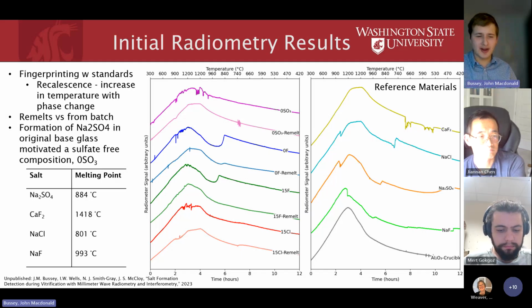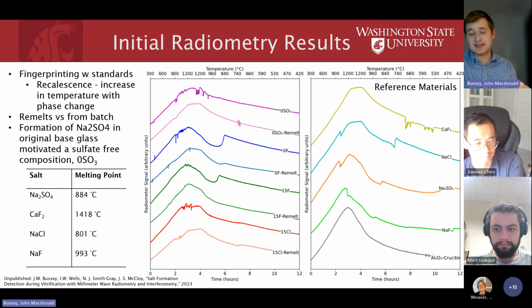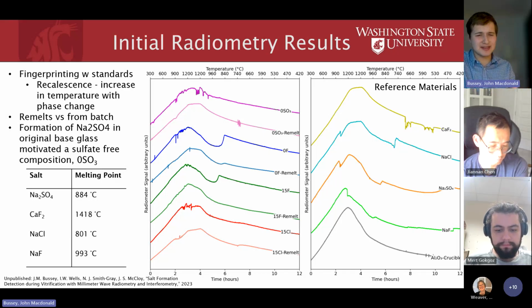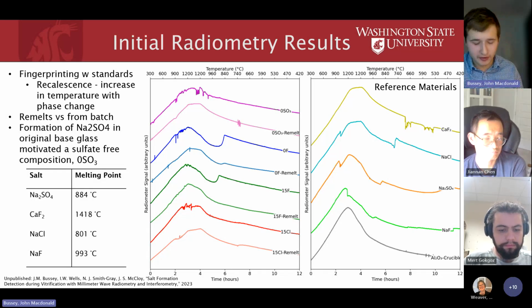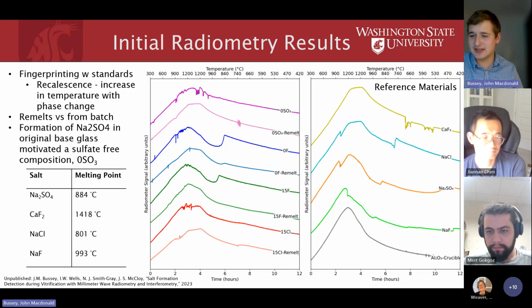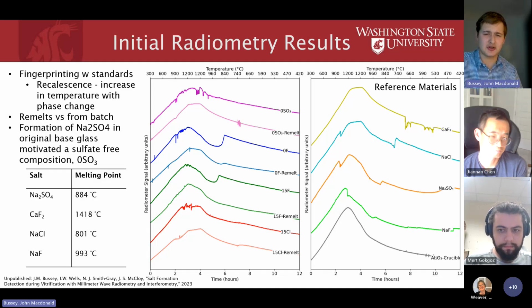So we measured 4 glasses: a chlorine glass that formed salt, a fluorine glass that formed salt, and then our baseline. But when we ran the baseline with this test that had no chlorine or fluorine, just 0.8% sulfate, we found some salt that formed. And so we were motivated to make one with no salt of any kind.